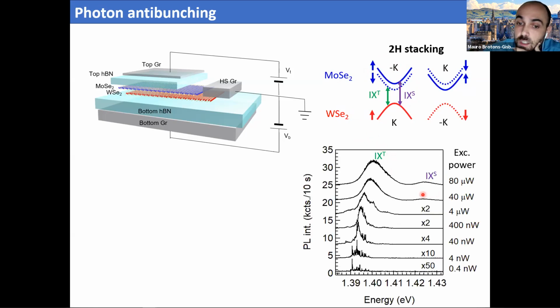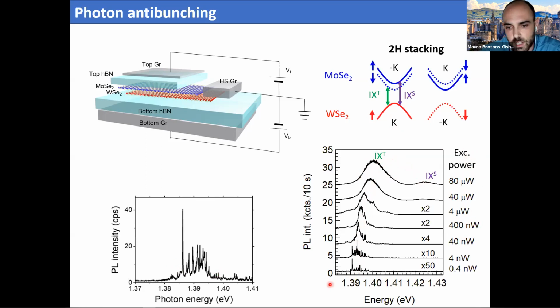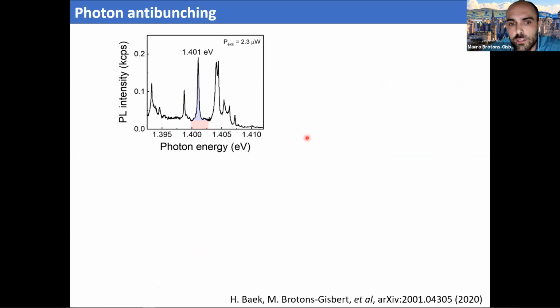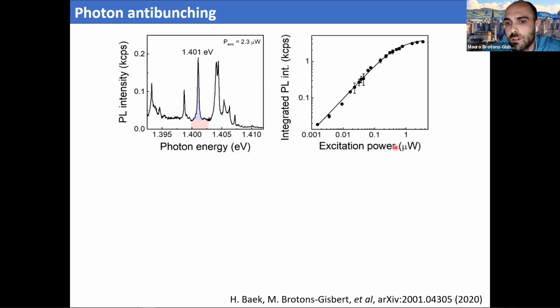And here I'm showing you the results of changing the excitation power. For high excitation powers, we basically see two broad bands, which are these two exciton transitions. In fact, the energy separation between these two is the spin orbit coupling energy difference between these two bands. And once we start decreasing excitation power, this band starts breaking into narrow emission lines. Here I'm showing this spectrum. So these narrow emission lines are these Moiré trapped excitons. And I want to show you that these trapped excitons show the typical saturation behavior with the excitation power of a two-level system, which confirms that these are trapped excitons.